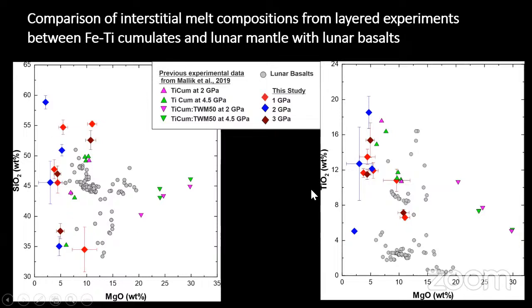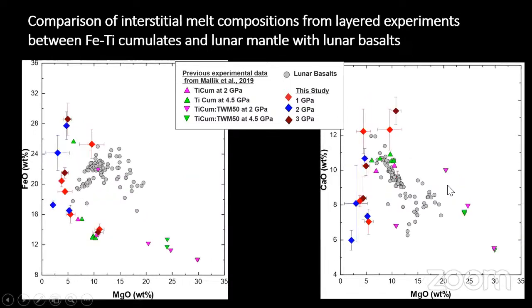The TiO2 compositions, however, are generally on the higher end of the lunar basalts. Lunar basalts can have low TiO2 or high TiO2. Our interstitial melts generally have a much higher TiO2 content, at par with the high Ti basalts or even higher, and not much in the low Ti basalt zone. These are the results from the mixed composition, which were also probably more in the high Ti zone.